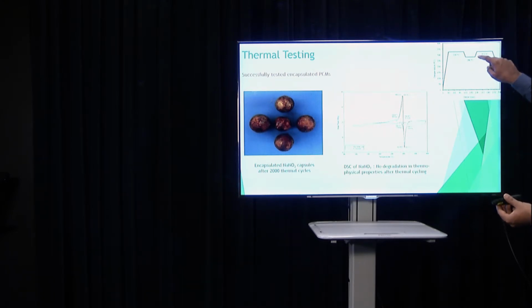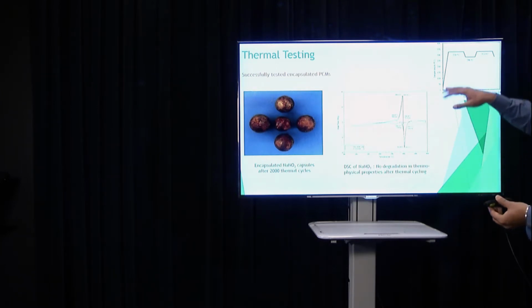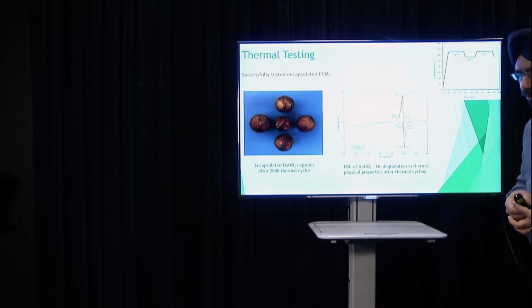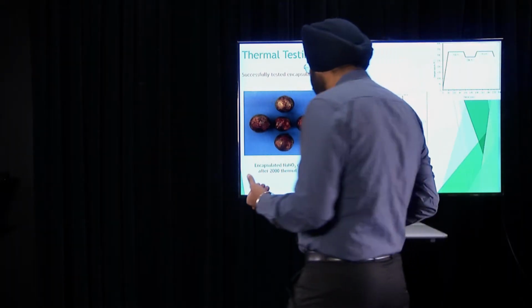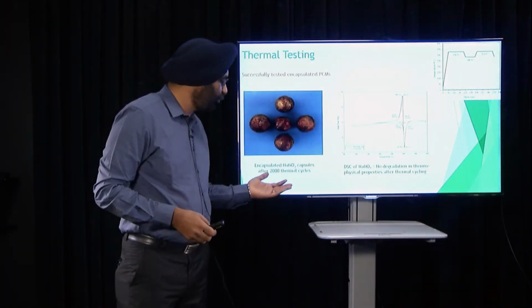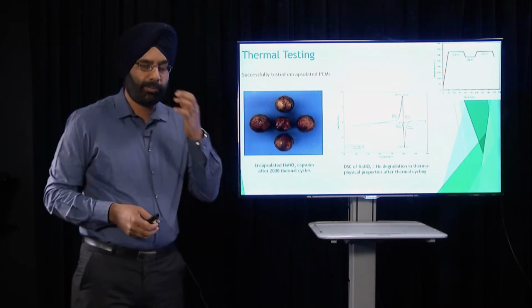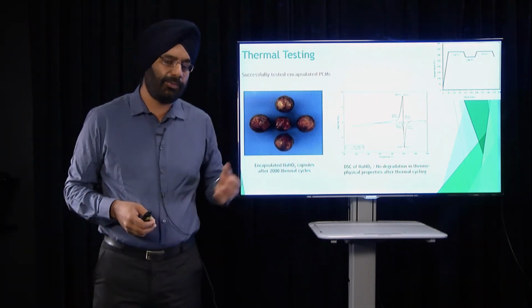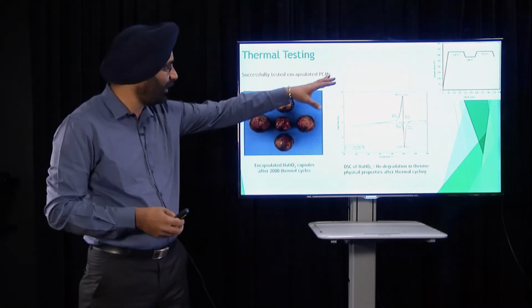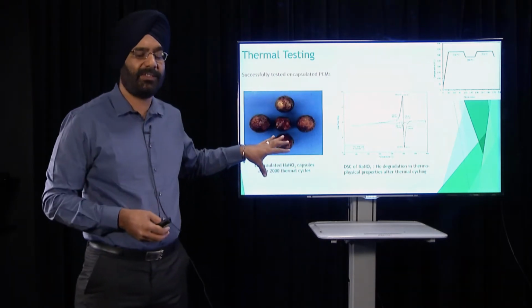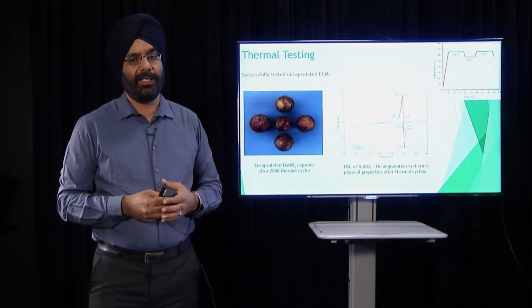And then when that happens, it was again heated to 326 and kept there for 80 minutes. So this was a cycle, a thermal cycle, which these capsules were subjected to a number of times. We tested these capsules for more than 2,000 thermal cycles. In fact, the latest figure is 2,500 cycles. So these capsules have undergone that many thermal cycles.